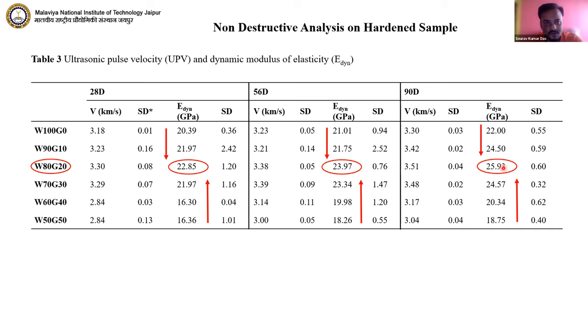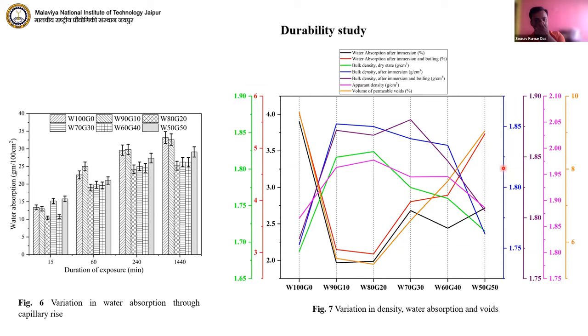Under the durability analysis, from the first figure, figure six, the variation in water absorption through capillary rise. Here, the minimum rise is obtained by the 20-30% or even up to 40% mixture. Beyond that, the rise goes up again. So we have a range of 20-40%, we can say. This kind of replacement will be helpful, not sticking to a certain point or a certain percentage, but 20-30% replacement is beneficial for long-term water absorption through capillary rise.